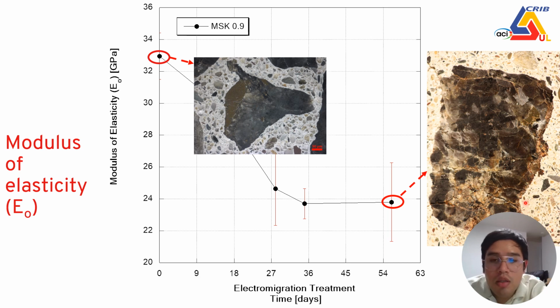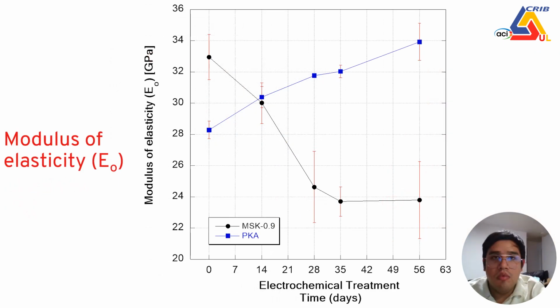Normally the reaction will start in the periphery, where the chlorides will reach and touch the iron sulfide minerals and will oxidize, and then these byproducts will generate an expansive reaction, forming cracking internally and in the cement paste too. But the most important result is that for the aggregate PKA, we did not generate any loss of the modulus of elasticity, so that can allow us to distinguish between a reactive and non-reactive material. The problem is that because they are different aggregates, from different quarries, the performance is not the same. So for that, we need to create a new measurement that can allow us to compare between one and another type of source of aggregate.